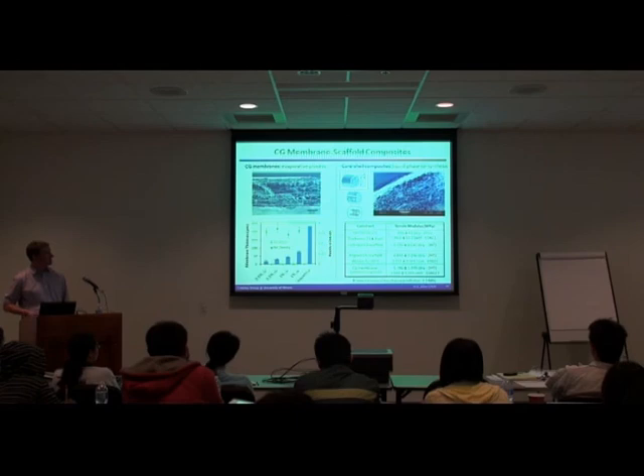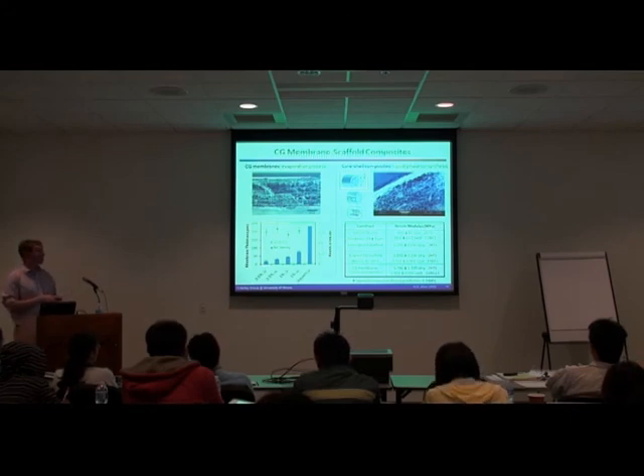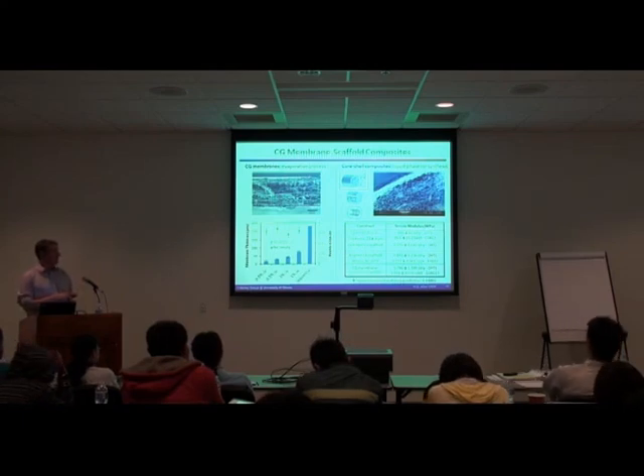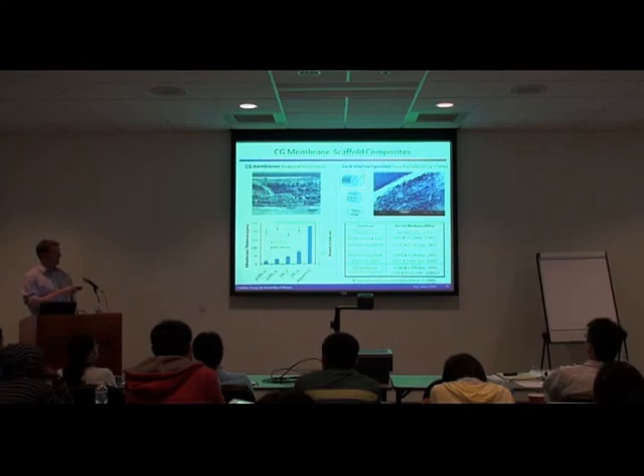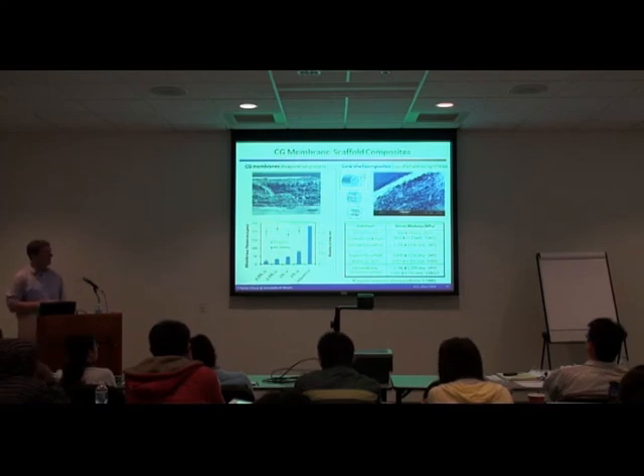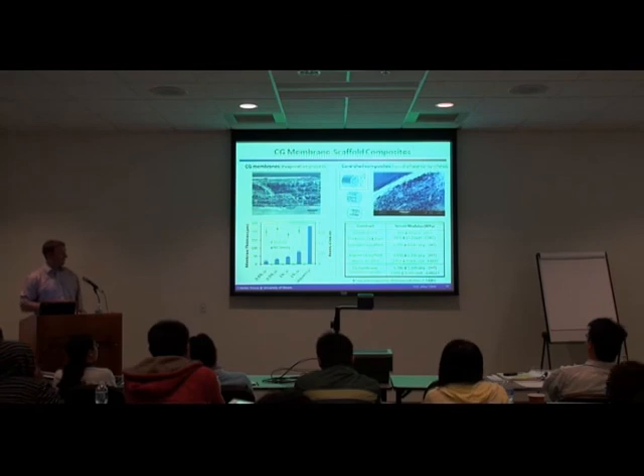So we thought it'd be fun to see if there's a framework we can use to produce our highly aligned scaffolds with a membrane shell around the outside, which produces porous shell composites. We've actually gone about making these membranes where they have a relative density of about 75%, so they're very, very dense and very, very stiff. We can change features such as the thickness of these membranes without changing relative density via some fabrication techniques. We can start making porous shell composites. This is the classic one with the shell around the outside of the porous core. We've also started to make a central core membrane or a partial shell membrane as well. The interesting thing is that it gives us some really high strength applications.